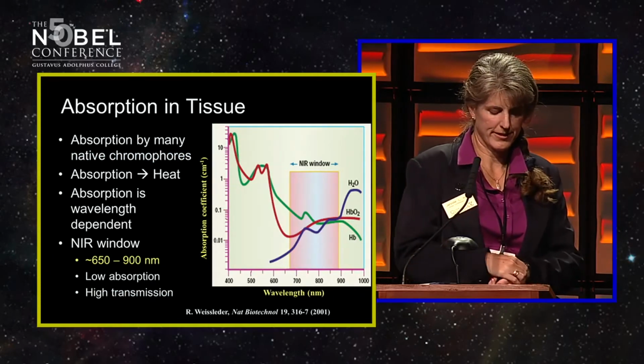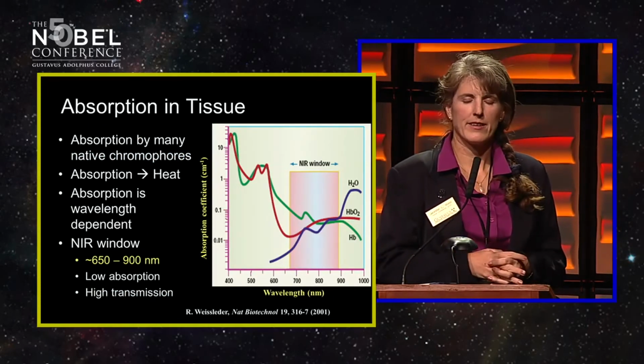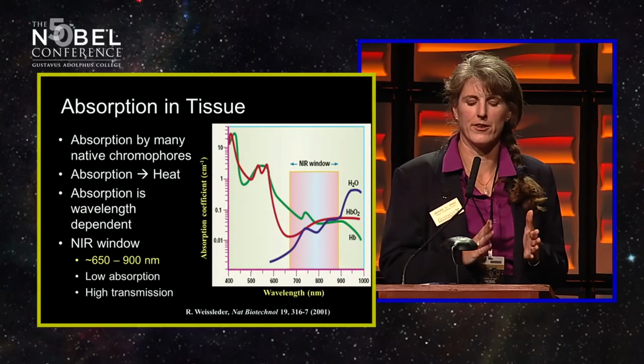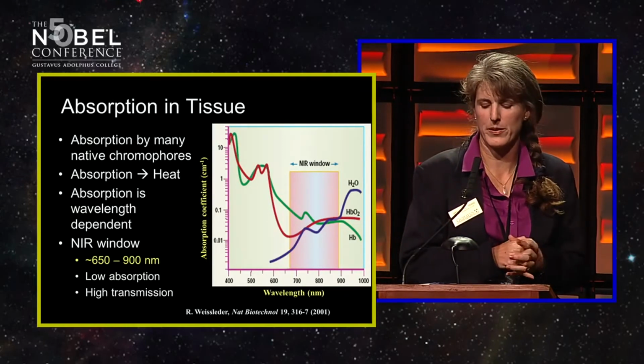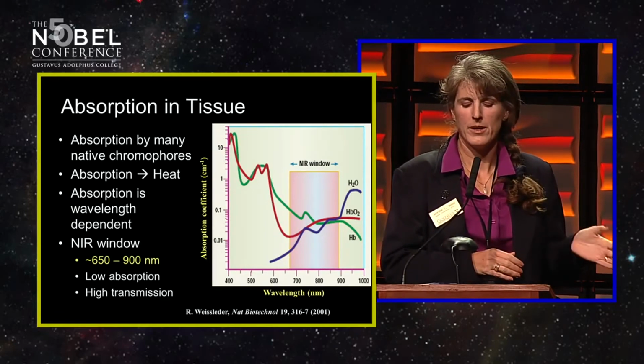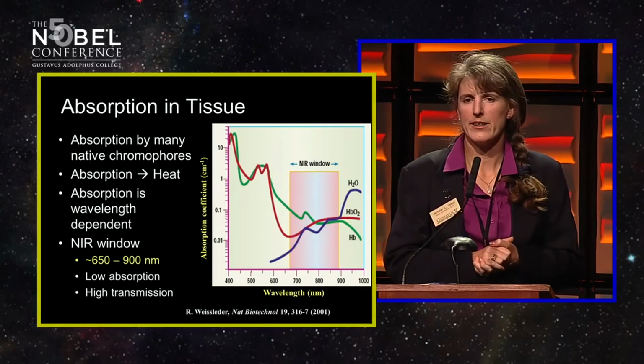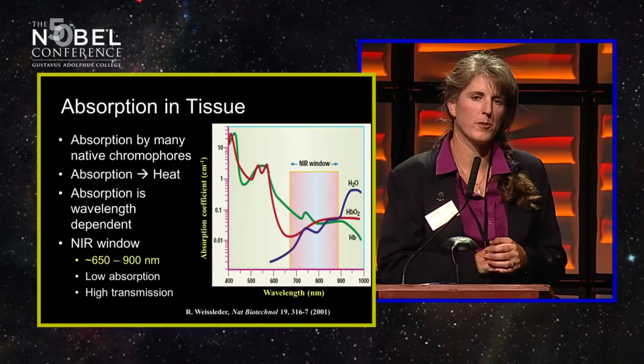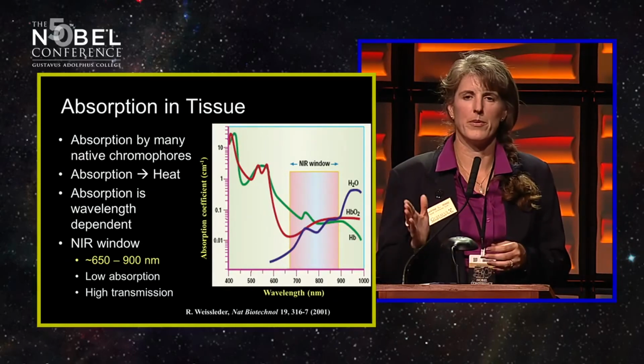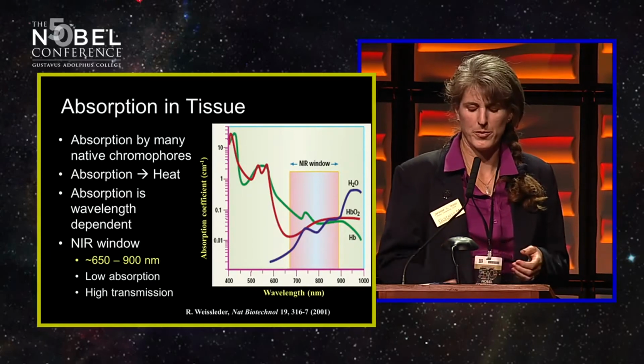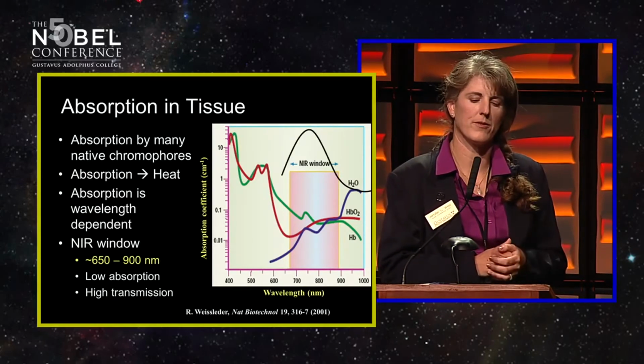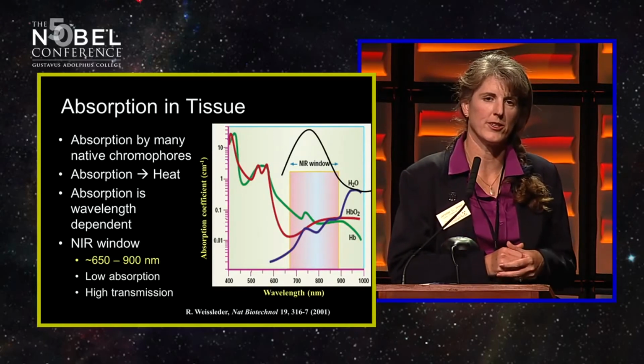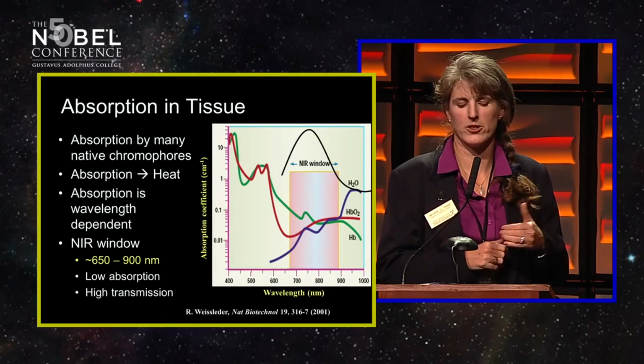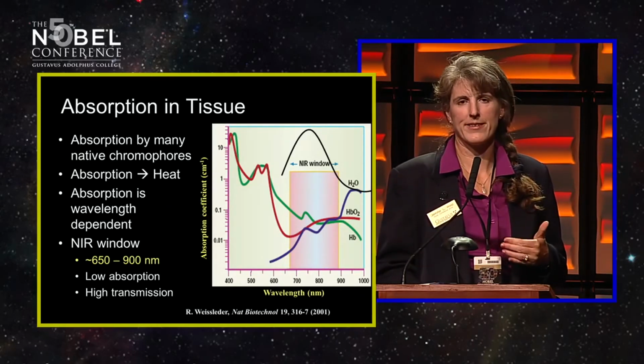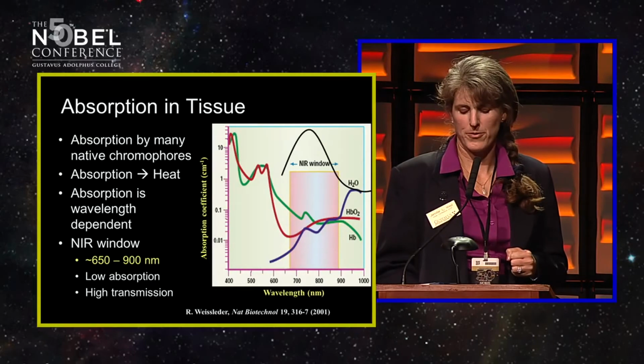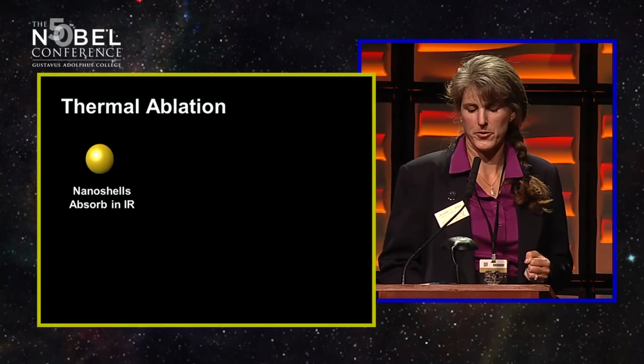We're choosing this near-infrared light because tissue in a small region of the electromagnetic spectrum is virtually transparent. Between about 700 and 900 nanometers, you end up above the absorption of chromophores like hemoglobin and melanin, but below where water starts to be a significant absorber. If you design your particles to have orders of magnitude stronger absorption than the tissue, you can set up your illumination conditions so that you have very safe light for the normal tissue, but induce rapid damage when the light interacts with the particles.